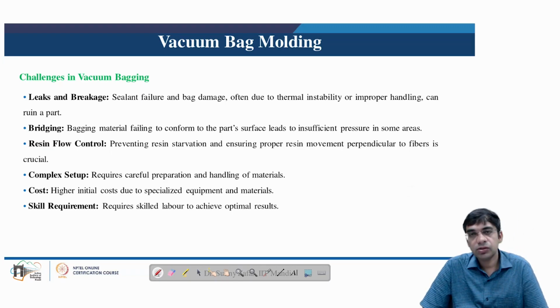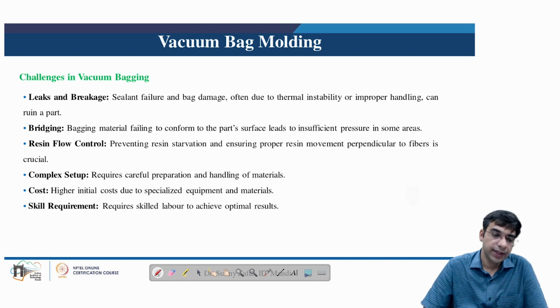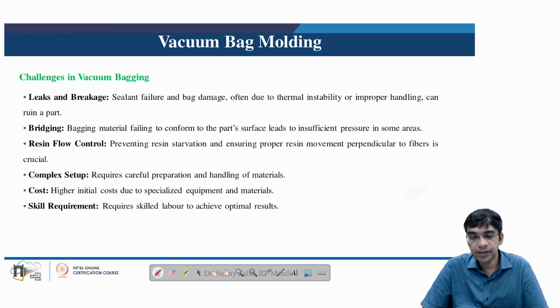Various challenges are also there in the vacuum bagging arrangement, as discussed now. There are possibilities of leaks and breakage, because sealant failure and bag damage may also result, often due to thermal instability and improper handling, and this can ruin the part quality. Bridging is another challenge, where bagging material may fail to conform to the part surface, leading to insufficient pressure in some areas. Resin flow control, preventing resin starvation and ensuring proper resin movement perpendicular to the fiber, is crucial.